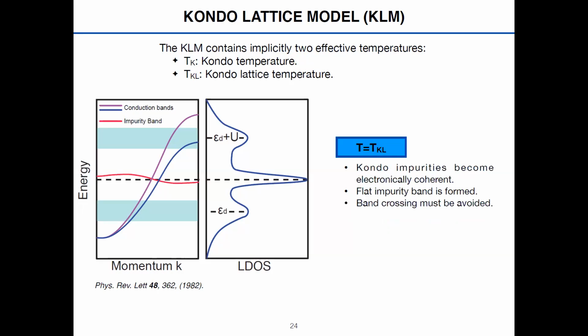When you are close or you are at the Kondo Lattice temperature, what happens is that these periodic Kondo impurities are no longer independent. Okay, they are now electronically coherent, and with the periodicity of your crystal. So the Kondo cloud, this magnetic moment with your conduction electrons screening it, starts to overlap with each other, and they become electronically coherent with the periodicity of the crystal, and therefore, with Bloch theorem, you should have a flat impurity band appear close to the Fermi energy.